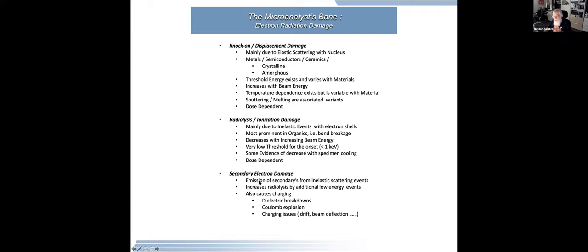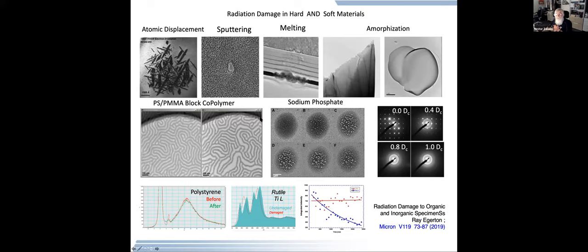And that manifests itself by a wide range of phenomena. We can get atomic displacement, we can get sputtering, we can get melting, we get amorphization, we get mass transport and mass loss. We get crystalline materials going amorphous. And we will look at the electronic structure, we see changes in either the low loss structure, the core loss structure, or if we're doing X-ray microanalysis, we see mass loss in terms of the X-ray emission. So all of this is important. I'm not going to spend any time talking about that. If you're interested, there's an excellent bit of work by Ray Egerton in Micron that you can look up.